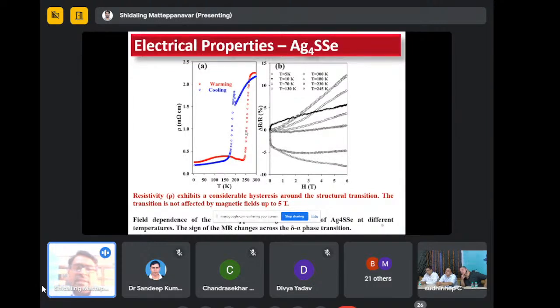So here we can see that at room temperature the resistivity is quite high, in the milliohm centimeter range, and when we cool the system from 300 Kelvin down to 2K, we have seen a sharp drop in the resistivity, and after that drop it continues. So initially we thought there might be some kind of superconductivity, but up to 2K we have not seen any zero resistivity in this sample.